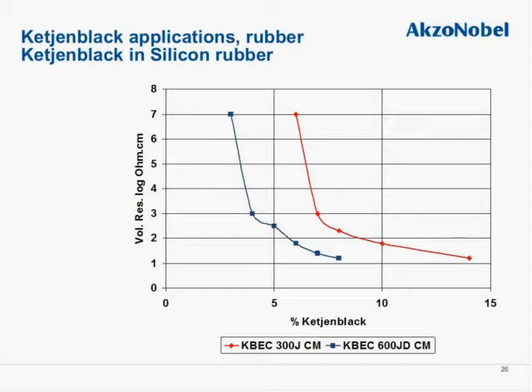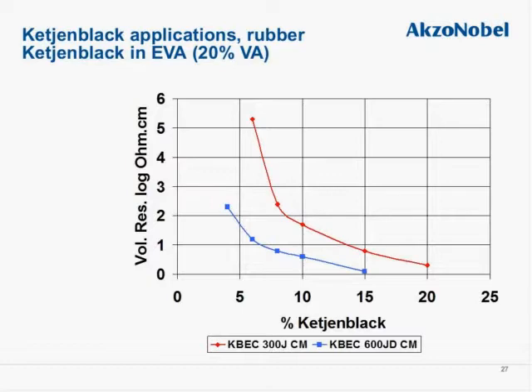Next example, in silicone rubber, in this case it is an elastomer, and again we are seeing fairly low levels of Ketjenblack for turning a silicone rubber into a fully conductive product, and both are compression molded. An example that I want to show is Ketjenblack in EVA with about 20% VA content. And in this case, both these products in side-by-side comparison in compression molding are showing extremely good conductivity at levels of additive being way below 10%.